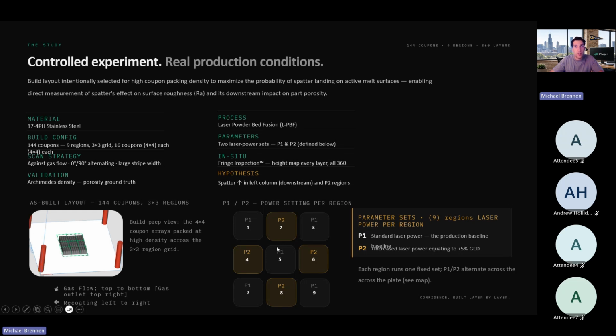Just going into the experiment, we weren't sure how effective building into the gas flow would be in terms of creating spatter. I think ultimately what we found was that we saw very little spatter effects from the higher GEDs, global energy densities, and the increased laser power, and we saw a much stronger impact from building into the gas flow, and that'll be apparent in the results.